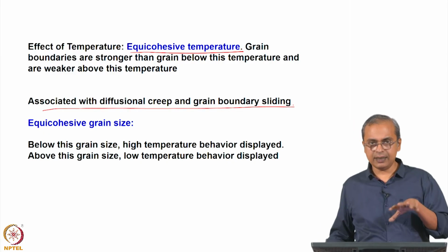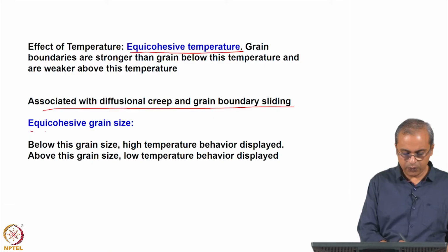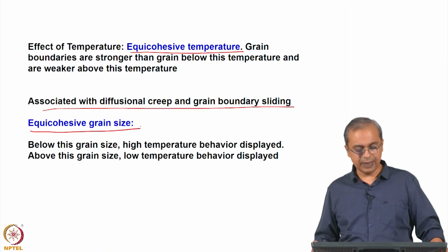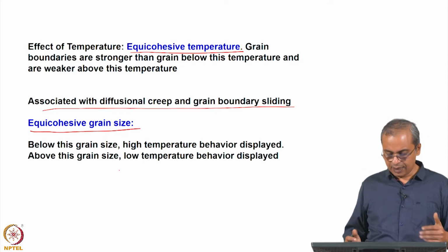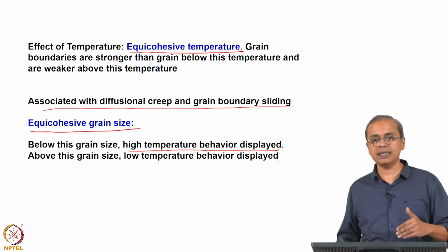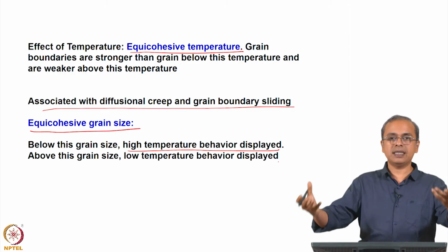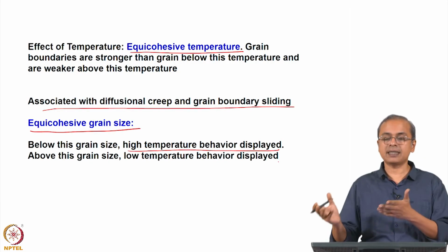Similarly, the original work on this area suggests that you can even have something called an equicohesive grain size, where below this grain size high temperature behavior is displayed, which means below this grain size the material acts as though it is sitting at high temperature, which means creep is high, which means grain boundary is weaker than the grain, right.